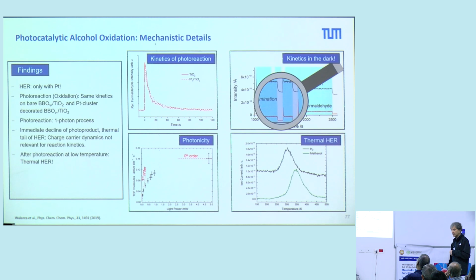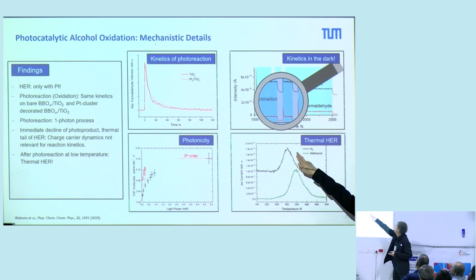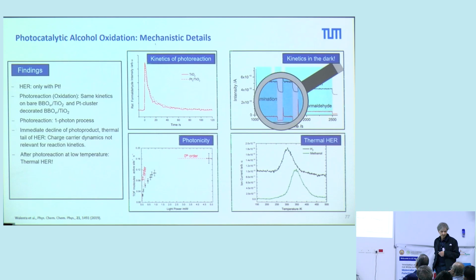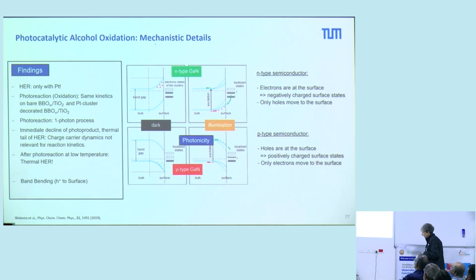And we can also do this at low temperature. That means we can somehow suppress the thermal processes, then we can heat up. And you see that the hydrogen is indeed formed in a thermal process. And then last but not least, of course, if you have a titanium dioxide crystal, it is undoped. That means we have a band bending that is upwards. That means if we shine light on this semiconductor, the minority species, which are the holes, go to the surface. The electrons go into the bulk. That means we have only holes on the surface. That means we do not need these electrons for the reduction. It's a thermal process. So this is also an indication that this is really a photo and thermal process.